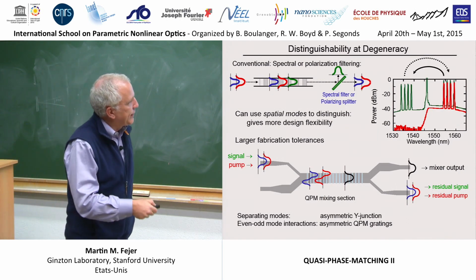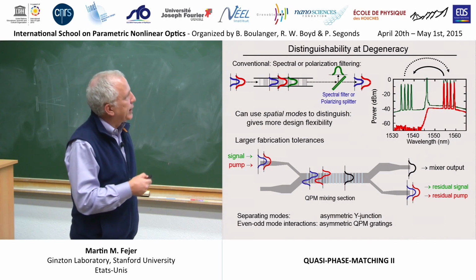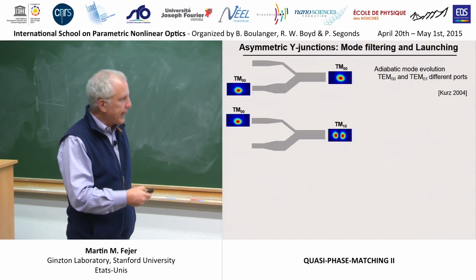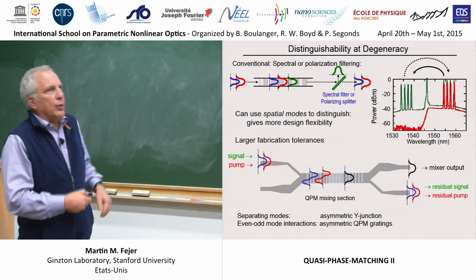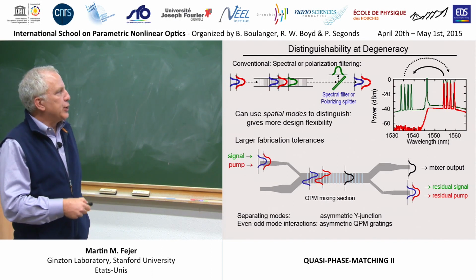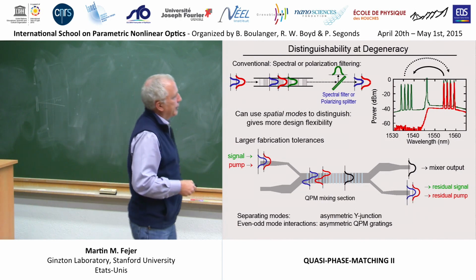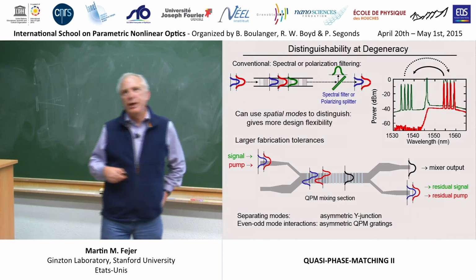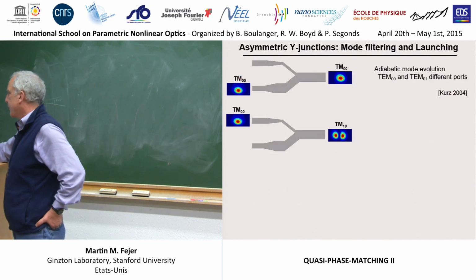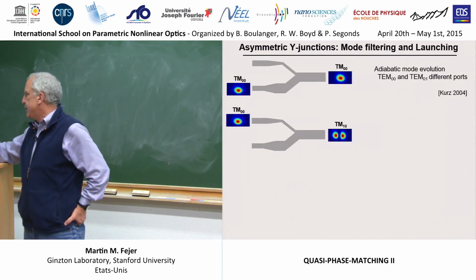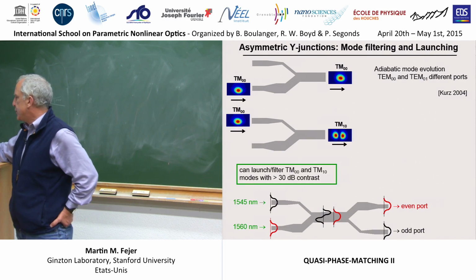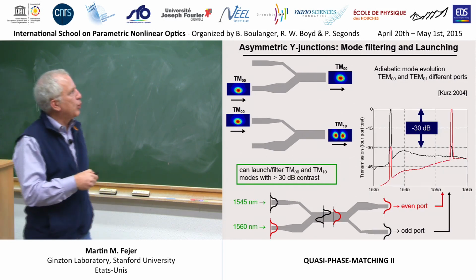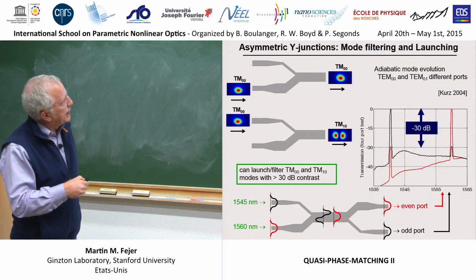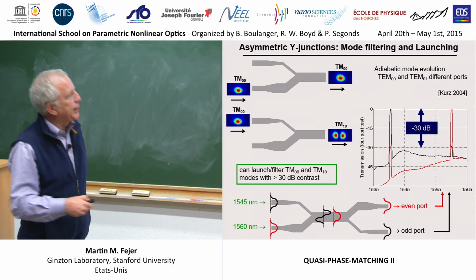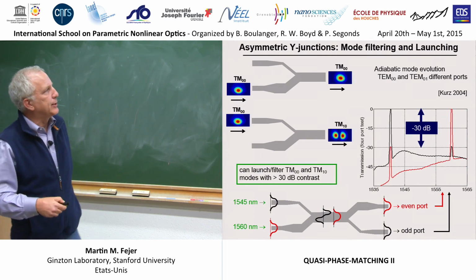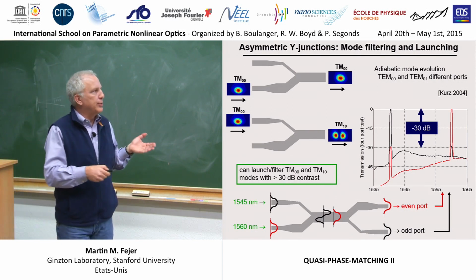So you can use this kind of structure to create distinguishability at degeneracy, not using polarization, which is inconvenient because you want to use the large nonlinear coefficients of this material, but through the spatial mode combinations you choose to operate with. This is an example of such an asymmetric Y-junction for doing this, either preserving the 0-0 mode or launching the odd mode, and you can get about 30 dB selectivity between these two arms using this kind of technique.